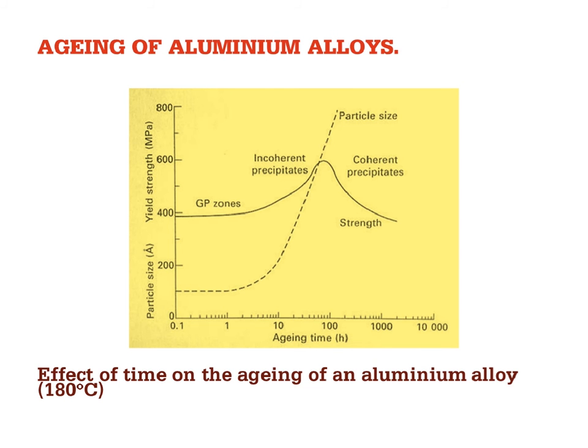Just to illustrate the importance of that in the aluminium circumstance, here we are looking at it as a function of time. So we've heated the aluminium alloy up, this is, let's say, a 2000 series, which has aluminium and 3% copper. Now at a high temperature, that 3% of copper will dissolve in the aluminium at around about 500 degrees. So we heat it up to that temperature.